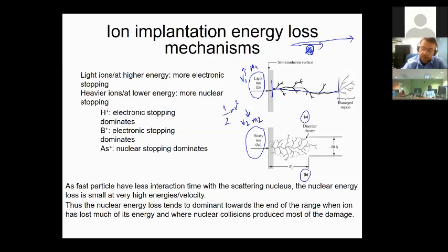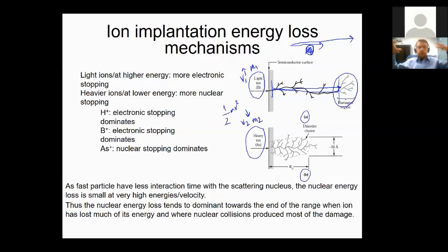So it will just not be scattered too much. Instead, it will continue its trajectory right along, just like a bullet. And it will start losing its energy, or speed, I should say, and then it will start colliding because it will start interacting. It reacts just like an electron. It will start seeing all these potentials applied on it. So it will start hitting the silicons more and more frequently, and it will damage the crystal there.